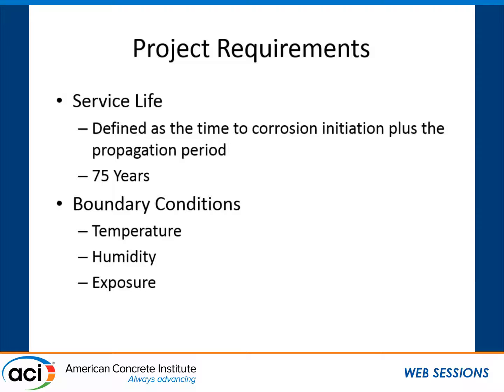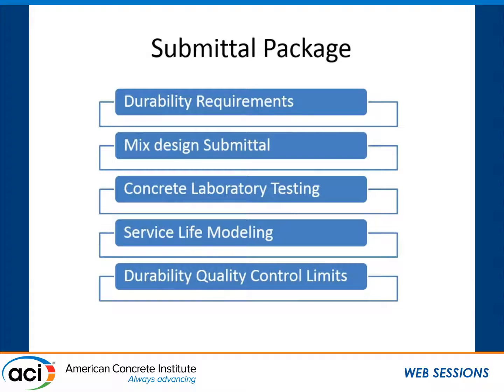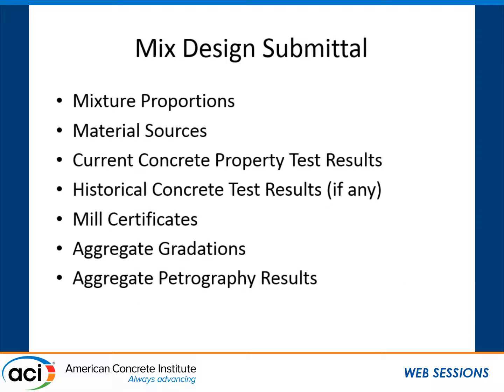What they did was to try to eliminate some of the guesswork and some of the variability that could occur. The Navy set a lot of the boundary conditions for the modeling itself: temperature, humidity, exposure conditions by element. So they put that together within the specification itself. The submittal package would then have your durability requirements by the element, the mixed design submittal, the concrete mix testing, service life modeling, and then the quality control plan. The mixed design would have the typical mixed design you would have: the proportions, the material sources, the concrete properties, the historical performance, the cement mill certs, and the like.